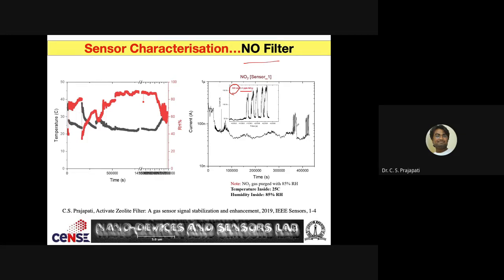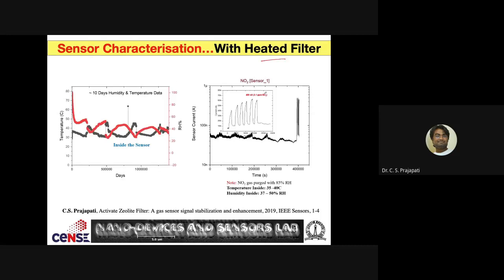Now when we put the heated filter here, you can see that change. First you see the change here: your humidity and temperature came into a certain window, and it is fluctuating within that. That's the beauty of the heated zeolite filter. Also you can see the baseline is quite controlled. Not that great, I would say, but compared to the previous one without filter, it is much more controlled. And you can see that for the same ppm of NO2, you have a much higher change in the current or resistance, I would say. Okay, so this is what you are looking for.